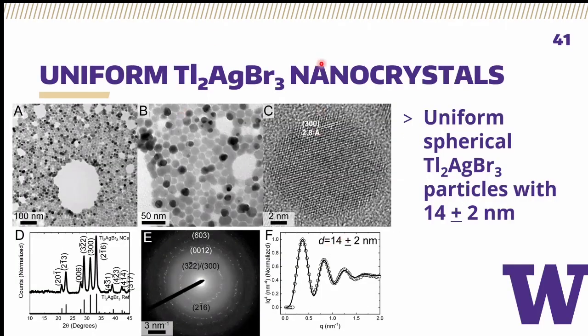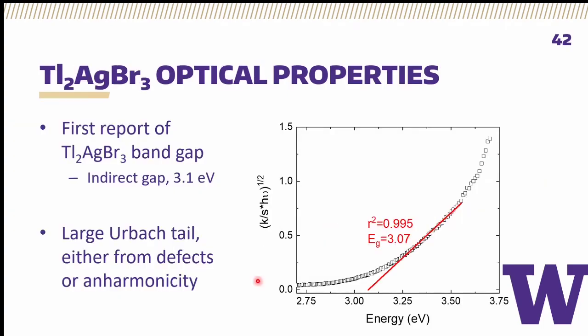The thallium silver bromide nanocrystals also had this nice uniform semi-spherical orientation, though could not be uniformly tuned. And this was the first time anyone has been able to show that they could synthesize this material, this crystal, in nanocrystal form. As it is a relatively unstudied material, we were also the first ones to report the optical band gap of thallium silver bromide and got a band gap of 3.07 electron volts in an indirect gap material from Kubelka-Munk analysis.